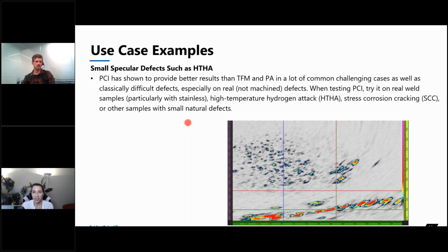When testing PCI, try on real weld samples. If it was in service, even better, because typically it's a bit more coarse. And we've seen also, particularly with stainless, if it is a simulated defect, it's not going to appear as well. High temperature hydrogen attack, HTHA, as we mentioned. Creep, that isn't listed there, but we've seen some very nice results with creep damage. Stress corrosion cracking, or SCC, and other samples with small natural defects is where we see this technique shine.